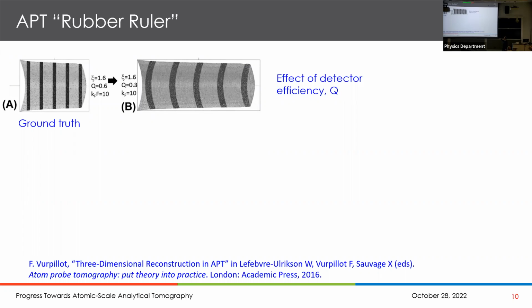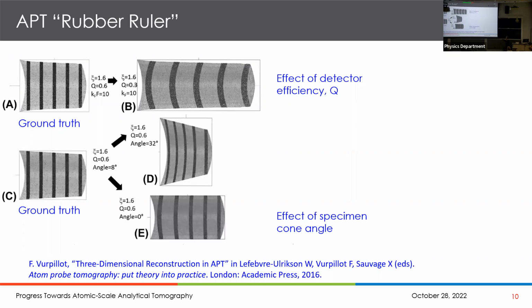But if you do everything correct, except you get the detector efficiency wrong, what you can see here is you get a different result. And in fact, not only is it expanded in Z, but these flat features are now curved. So this is a rubber ruler. There's another illustration. If you don't know the cone angle of the specimen, but you say, well, it's about 5 degrees, you can make some kind of guess, 8 degrees. Or if you put a large one, you can see the change of the reconstructed volume, say for a 32 degree versus, in this case, a 0 degree. So this is the effect of cone angle on the resultant image. And the bottom line is that this is not an acceptable outcome for imaging. We need high spatial fidelity.